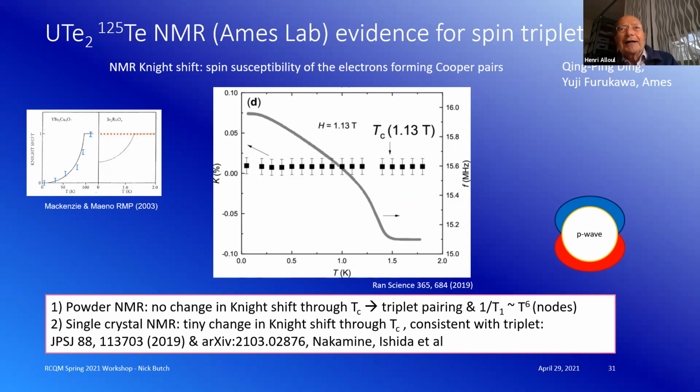When you have a large T dependence of the susceptibility in the normal state, you can get the hyperfine coupling by measuring the shift versus temperature in the normal state. Then you can see which fraction of the shift is killed when you enter the superconducting state. If they cannot measure it in this direction, it's a problem, but they should be able to. Why is it impossible?